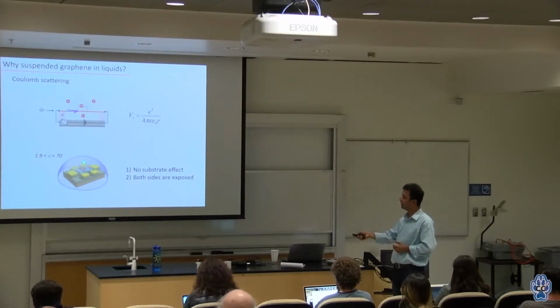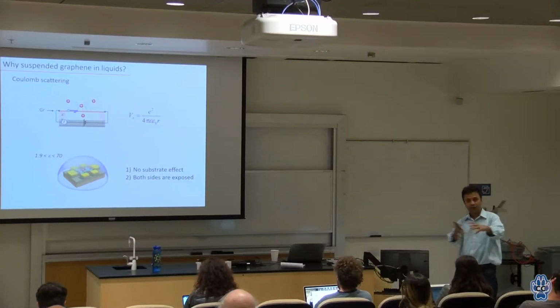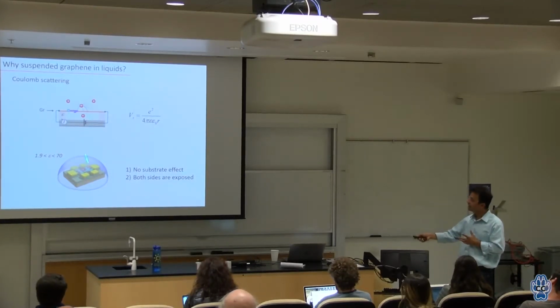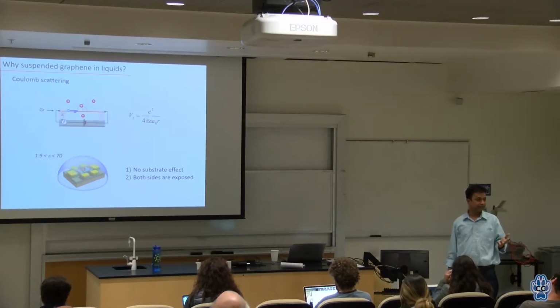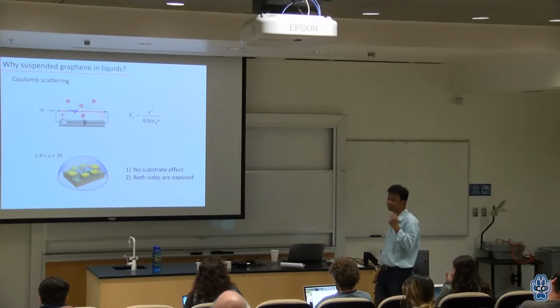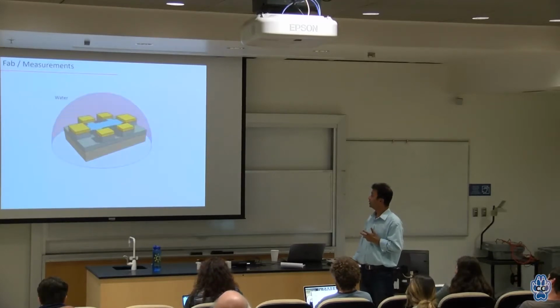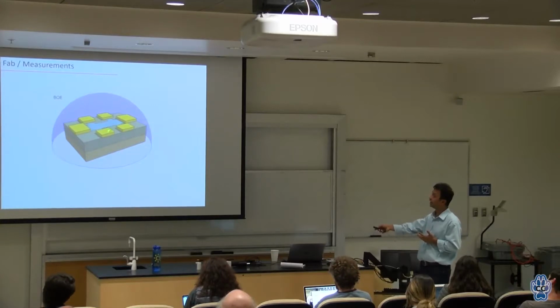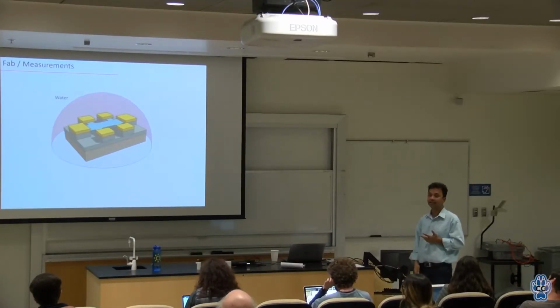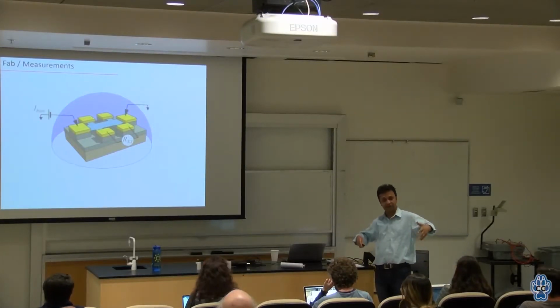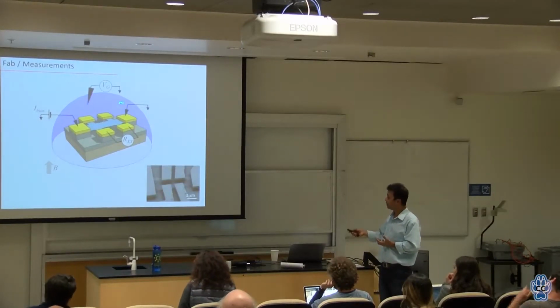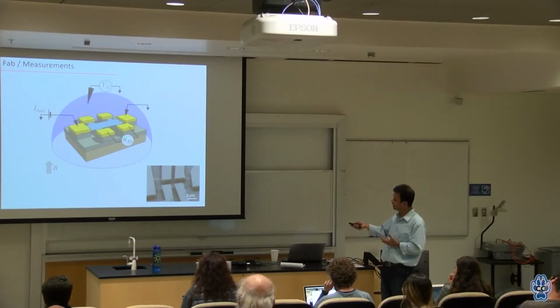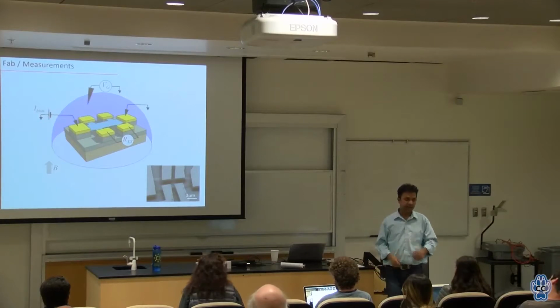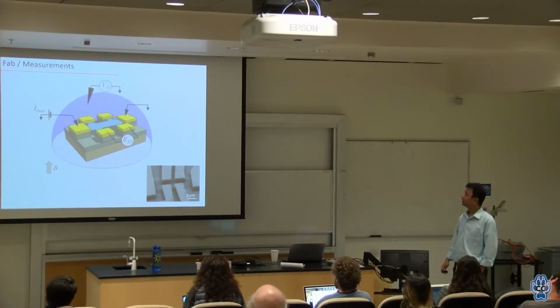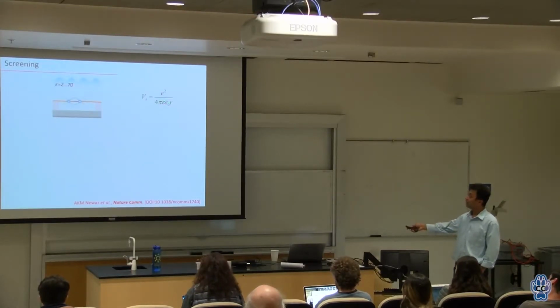We made graphene devices suspended in liquid, flushed the liquid and measured the electrical properties, then put in a new liquid and measured again. And we showed that, indeed, when you have a higher dielectric constant, your graphene gets better. That tells you that it is indeed the long-range Coulomb scattering that is determining the electrical properties. For the fabrication, you start with graphene on silicon dioxide, then we have a way to remove the substrate underneath it, and then you put on all the electrodes, put the whole thing in a magnetic field, and measure the electrical properties. This is a scanning electron microscope image of a Hall bar shaped graphene device in vacuum.